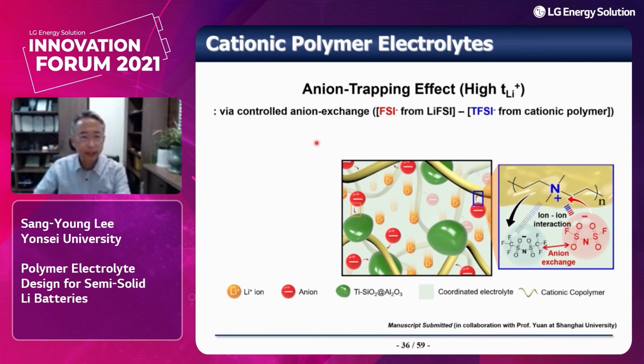So we are interested in the anion trapping effect to enable a high cation transference number. The fundamental technology is based on controlling anion exchange. As a lithium salt, we have chosen LiFSI, and as a cationic polymer, the TFSI anion was attached like this. Here the FSI anion and the TFSI anion can be exchanged like this.